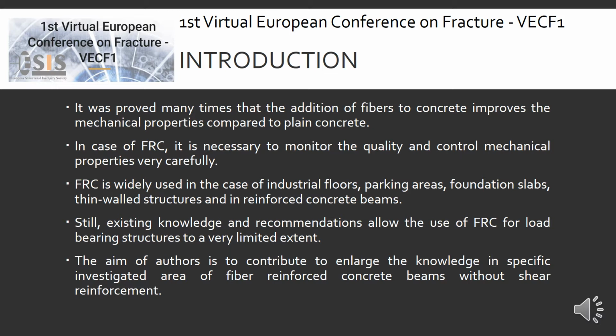It was proved many times that the addition of fiber to concrete improves the mechanical properties compared to plain concrete, especially tensile strength. In case of fiber reinforced concrete, it is necessary to monitor the quality and control mechanical properties very carefully. Fiber reinforced concrete is widely used in the case of industrial floors, parking areas, foundation slabs, thin wall structures, and in reinforced concrete beams.